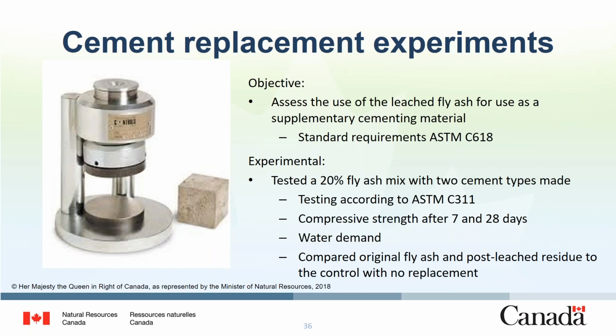As noted earlier, one of the more important aspects of reprocessing coal fly ash is the fact that it may be possible to completely eliminate the process waste, as long as the leached residue is suitable to use as a supplementary cementing material. In order to test this, we used ASTM standard C618 to assess the use of the leached fly ash for use as a supplementary cementing material, according to the test as listed on your screen.